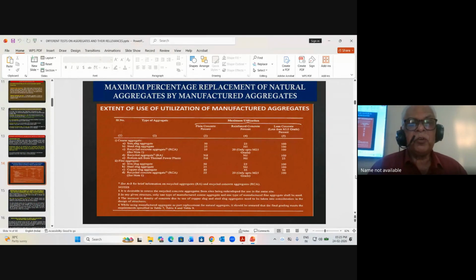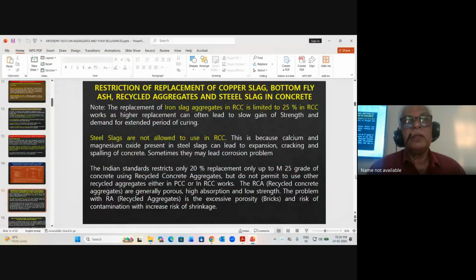There are reasons for that, some of which I'm going to highlight here. Replacement of iron slag aggregate in RCC is limited to 25% in RCC works. This is because higher replacement can lead to slow gain of strength and demand for extended periods of curing. This is a disadvantage with iron slag.